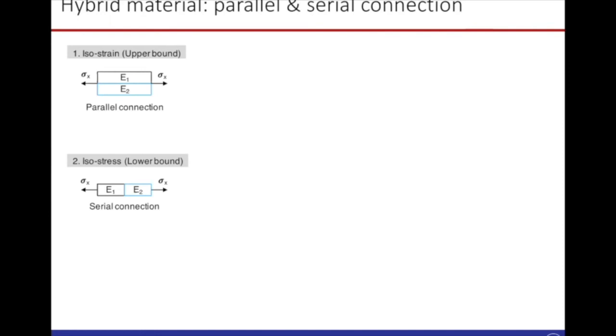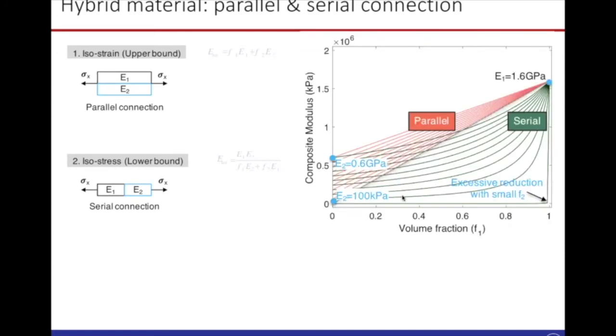To obtain a large change in membrane stiffness, we put forward this concept of a hybrid fiber using hybrid material. It's simple: if you choose 2 materials with stiffness E1 and E2, you can connect them either in a serial connection or in a parallel connection. And the effective stiffness will be given by this equation. Now, if you plot these 2 effective stiffnesses with respect to the volume fraction of the first material F1, you can get this graph. For a specific choice of E1, which is 1.6 gigapascal, we consider it as highly stiff. But E2 takes a range of values starting from 0.6 gigapascal, which is moderately stiff, to 100 kilopascal, which is almost soft material.